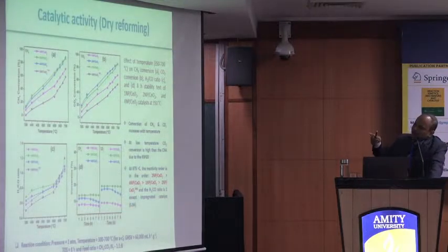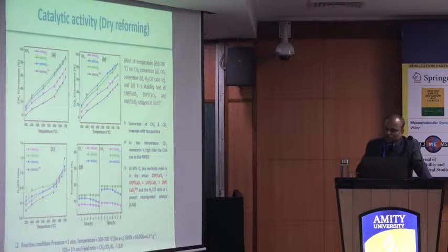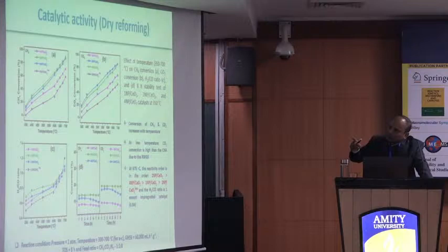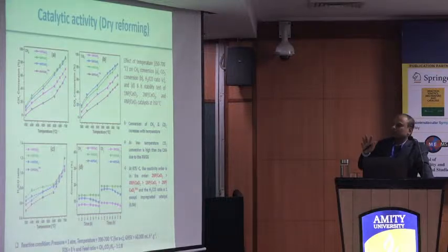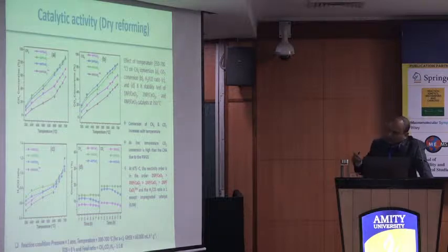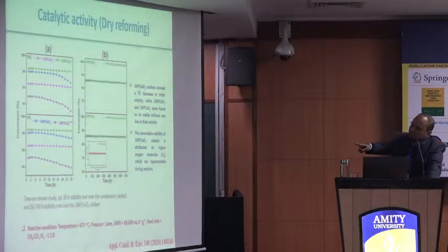Now this is the catalytic activity study. Here also you can see that our catalyst is very active even at very low temperature. We have found that at 350 degrees centigrade the catalyst is showing around 15% conversion. And at 675 degrees centigrade the catalyst is giving more than 95% methane conversion and more than 90% CO2 conversion. And this catalyst is stable even for 700 hours.